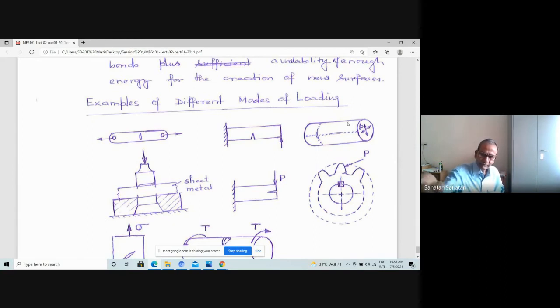And then if you think of, let's say, a pressure vessel which has both circumferential and longitudinal joints, the joints have the possibility of containing a crack, and this crack can be in the weld direction itself. So if you have a longitudinal weld, then the pressure which is acting inside the vessel is going to give rise to both hoop stress and axial stress.